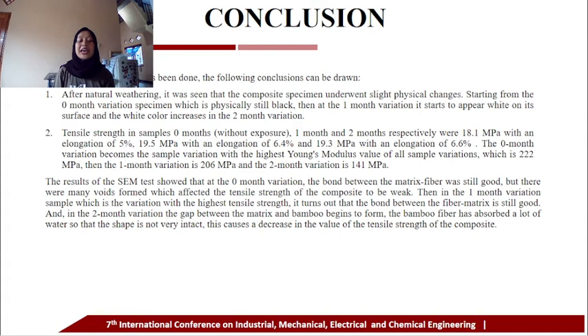The 0-month variation becomes the sample variation with the highest Young's modulus value of all sample variations, which is 222 MPa. Then the sample with one month of exposure is 206 MPa, and then the last, for the 2-month variation, is 141 MPa.